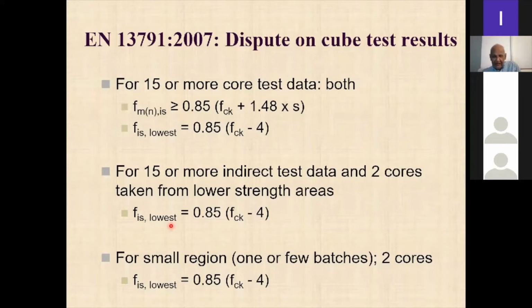That is the equivalent cube strength you get from the core, which should not be less than 0.85 times fck minus 4, right? And if you have a very small batch of concrete, now it's debatable what a small batch is, maybe if you have one truck, that is enough. So sometimes, typically, in these disputes, you find that the cubes from one truck have failed, right?